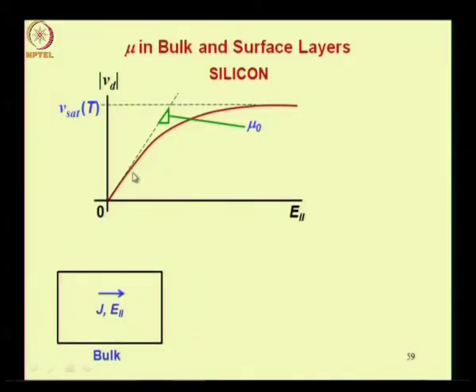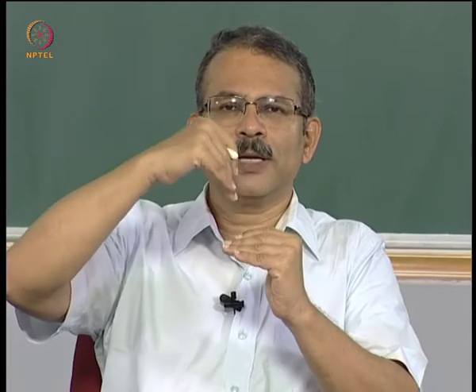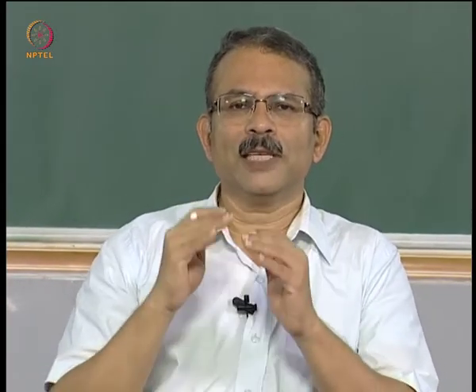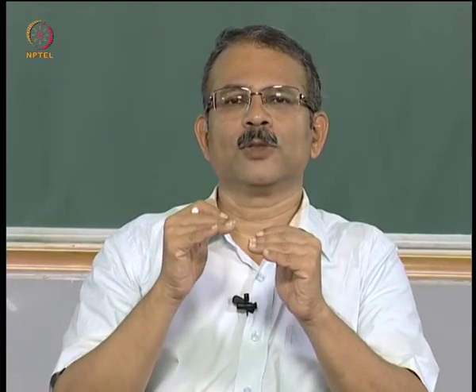Two limits of this drift velocity curve are shown here. One is the saturation limit, and that is indicated by the saturation velocity, which we shall see is a function of temperature, and the second limit is near the origin, the quasi equilibrium or ohmic region, where at low electric fields there seems to be a straight line behavior between the drift velocity and the field, and the ratio of the drift velocity to field is denoted as the mobility, and mu suffix 0 here, the suffix 0 indicates low field mobility. Now since we are in general going to encounter both parallel electric field and perpendicular electric field, we need to understand that when we use the term low field mobility, we always mean the field parallel to the current flow, okay. So it is E parallel.